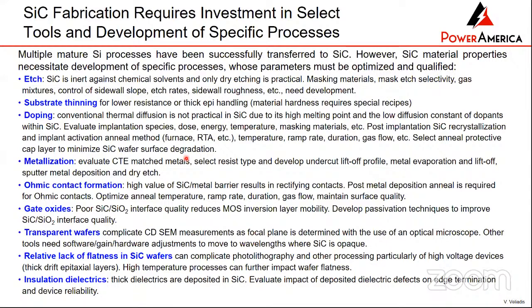But there are certain processes in silicon carbide that you cannot use from silicon. The areas where you need to develop technology for silicon carbide fabrication start with the etch. Because silicon carbide is inert, you cannot have a wet etch, you can only have dry etching, and that dry etching is very, very slow, but silicon carbide is a very hard material. The second thing is to thin the substrate. As I showed before, the substrate resistance can be a big contributor to the overall resistance, so you have to have techniques to thin the substrate. Obviously, to make any semiconductor device, you need to be able to dope, so you can get P regions and N regions. In the case of silicon carbide, doping can only be done by implanting.